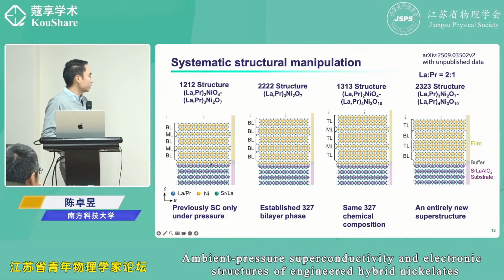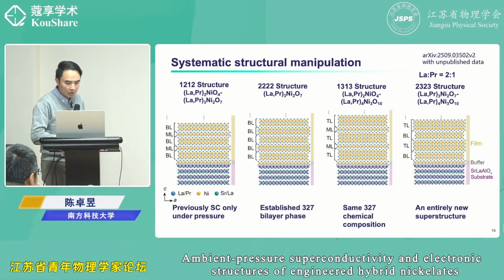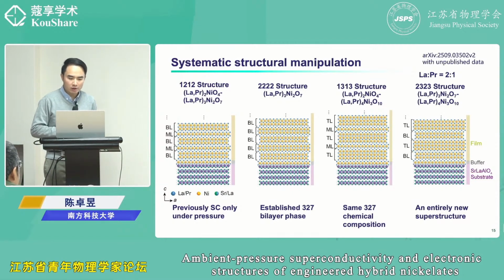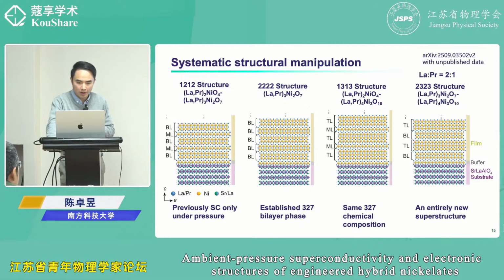This 1-2-1-2 is actually also synthesized in bulk form, and superconductivity is achieved under high pressure. And this 1-3-1-3 is the same chemical composition variant. The structure is completely different from this 2-2-2-2, but they are both 3-2-7 in chemical composition. And this 2-3-2-3 is maybe more difficult to synthesize in bulk form. But using this atomic layer-by-layer thin film method, we can construct this complex superstructure.